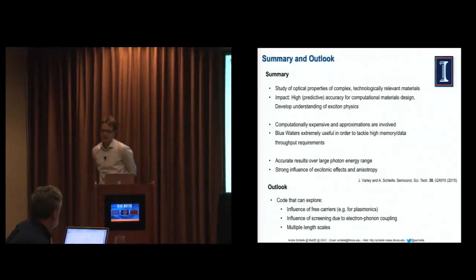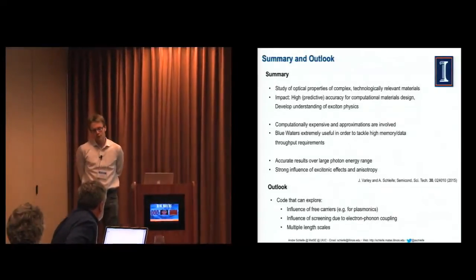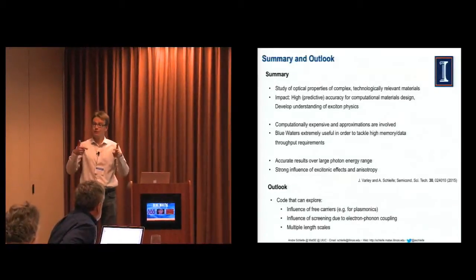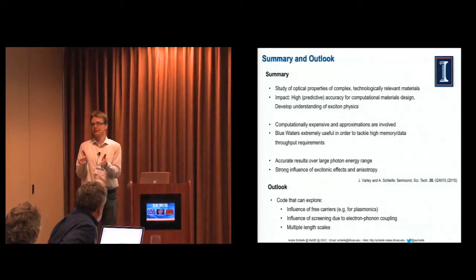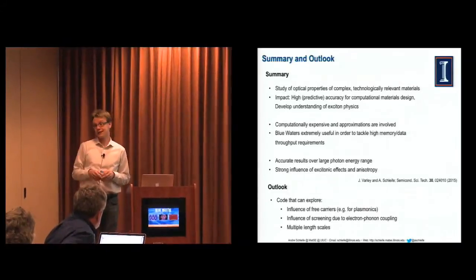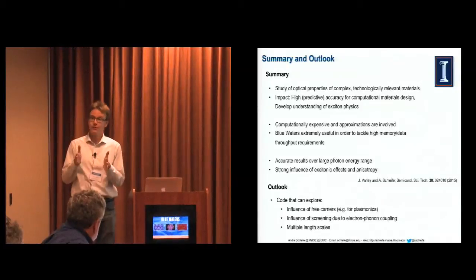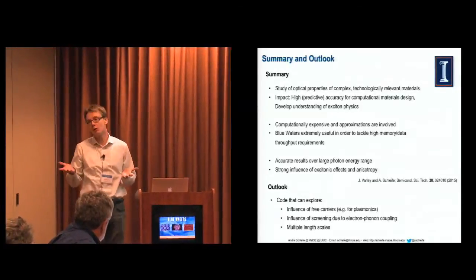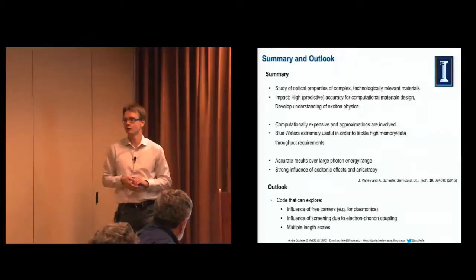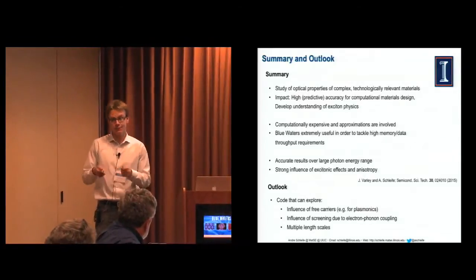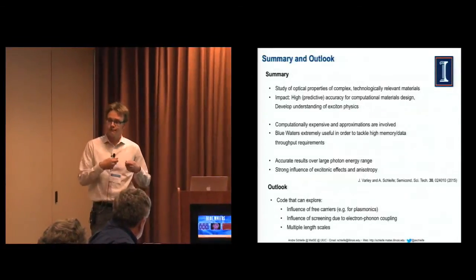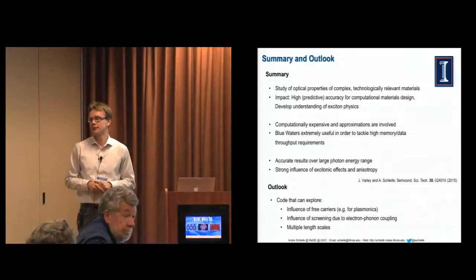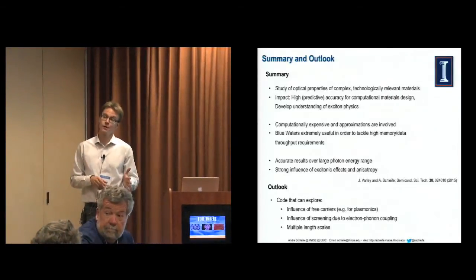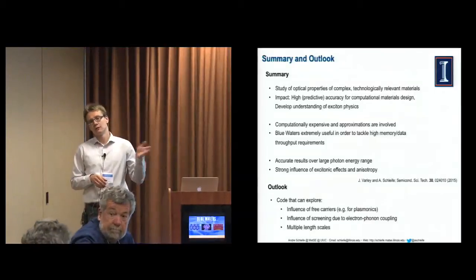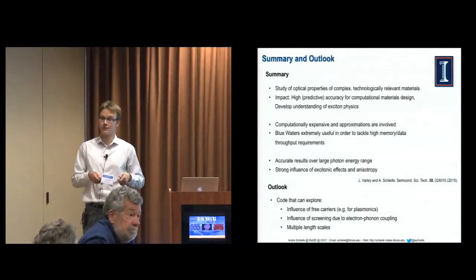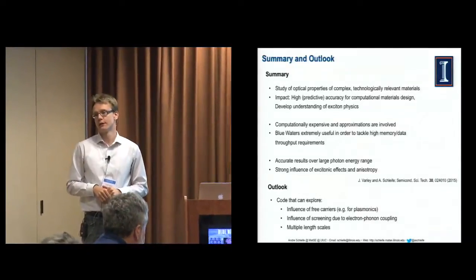Exactly. The 40 eV run is something where the fact that these collaborators have the capability of measuring that accurately is an opportunity for us to verify exactly these kinds of approximations. If you just care about a material for optical absorption, you're probably fine calculating it between 0 and 5 eV or something like that. But for us, this is an opportunity to get good testing material, so we can really compare to a good experiment. We can disentangle what's the effect from the quasi-particle corrections, what's the effect of the screening, and so we can improve that.